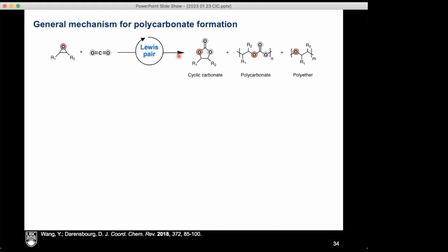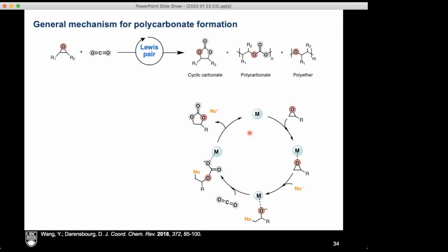And polycarbonate is actually harder. Forming cyclic carbonate is quite easy, actually. And polyether, I showed you, can form relatively easily. So the mechanism here is basically taking whatever metal source that you have, coordinating the epoxide, and nucleophilic attack, by an external nucleophile or a nucleophile that's bound to the metal, to ring open the epoxide, then coordination and attack of the CO2, and either an intramolecular attack to give a cyclic carbonate, or an intermolecular reaction with addition of another epoxide and another CO2 to form a polycarbonate. And the key to this is to be able to control going this way or going this way.